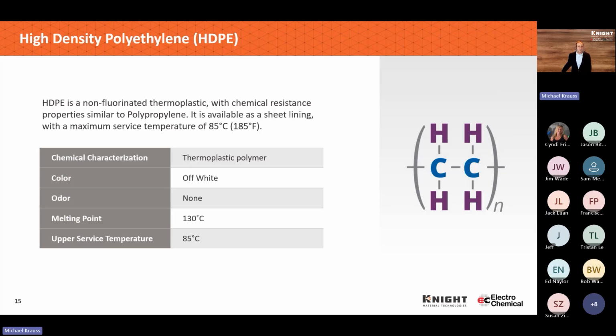As we look at the specific materials, I started here with polyethylene. It's not typically used as a lining material, either in lined steel or in dual laminates, but it's one of the most prevalent plastics out there. It's got decent chemical resistance in general to about 85 degrees Celsius, 185 degrees Fahrenheit. What you see here on the right side is the composition.